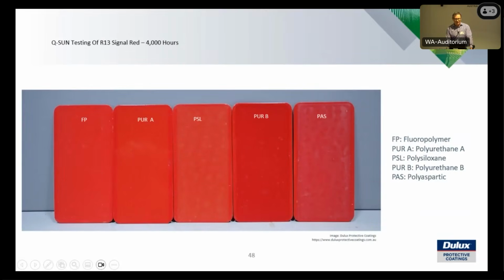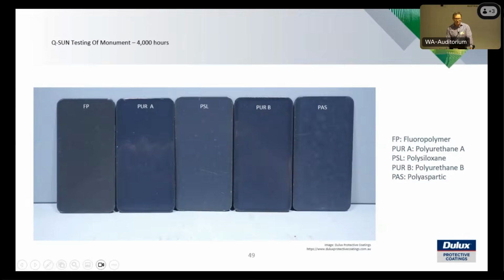But in the red, it's a completely different story with these particular test panels. They're all showing some signs of colour loss or some sort of chalking. As well as the Monument colour, all fairly similar, not too bad, a better performing colour in that test, because they're all fairly similar in that result there.